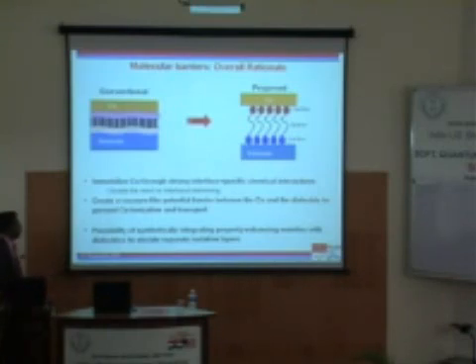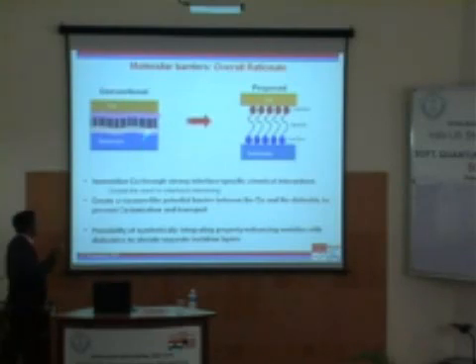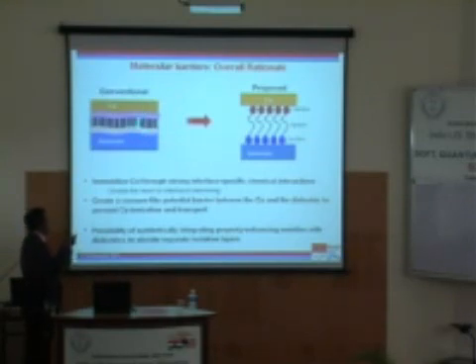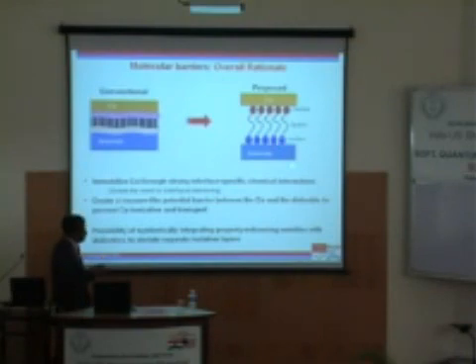So we tried a completely wild idea. This was an undergraduate project actually of 5 years ago, and the amazing thing is it worked. And of course, we have been exploring various aspects of this for the last several years. The idea is, instead of taking a brute force approach, which works quite well for micro scale but doesn't work well for nanoscale, where you put tantalum or tantalum nitride or some other material where the interaction is minimized to some smaller length scale, and these two stay separate and everything is fine. But as I said, you need a critical thickness of this for this to work. So we said, let's take molecules with certain groups on top, certain groups on the bottom, and these are going to be CC bonds essentially, which are very happy. And this is going to create a vacuum-like potential between these two materials.